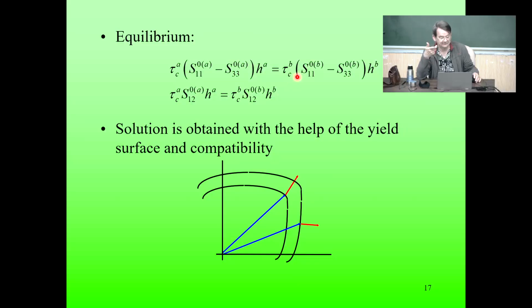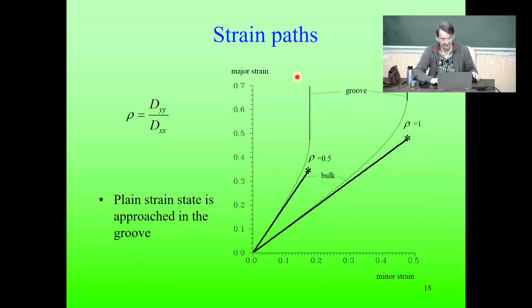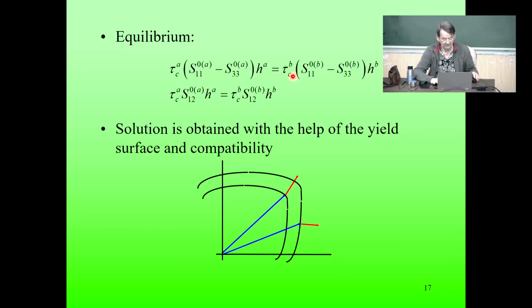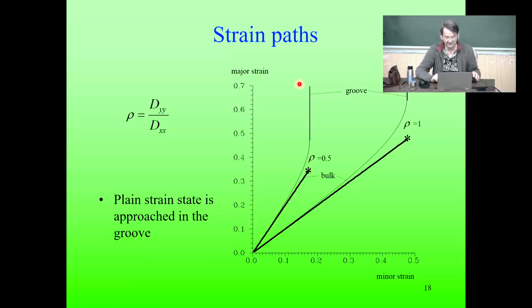We have to find out what is the stress state in both regions, and then satisfying these equations, we will get how the thickness within the groove is reducing. So to get the stress states in the two zones, we use polycrystal plasticity, using the yield surface and compatibility, right. But now let's go into the strain paths. What is happening during this Marciniak theory is a presentation of the so-called minor strain in FLD and major strain. For the positive part, and also for the negative anyway, plane strain state is approached within the groove.